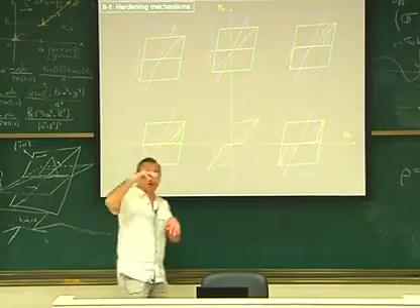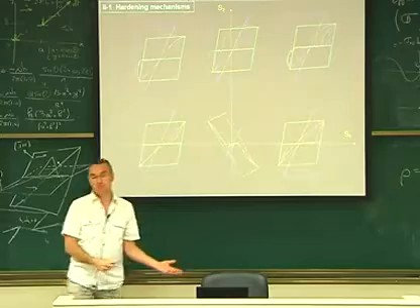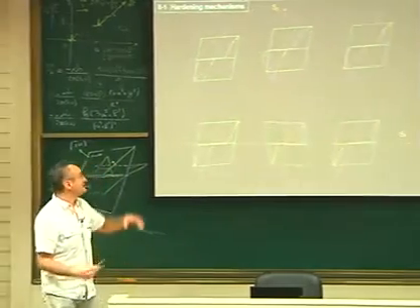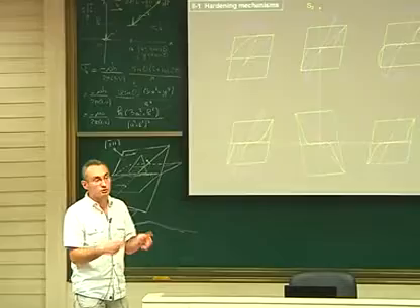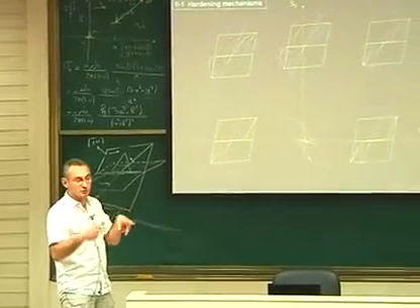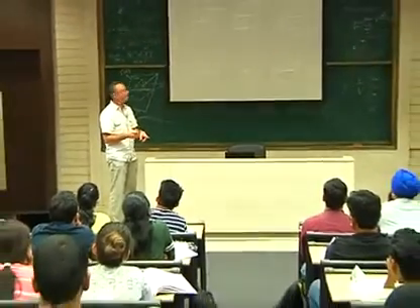So here I increase the stress step by step, and I measure the stress when it breaks. The same way as I did with the line tension model, except that here I have one more ingredient, which is the internal stress. I take into account not only the energy, but also the fact that the two dislocations interact with their stress fields. Okay? So this we will do next week. We will create a junction and break it. You see, we create and we break. This is life.